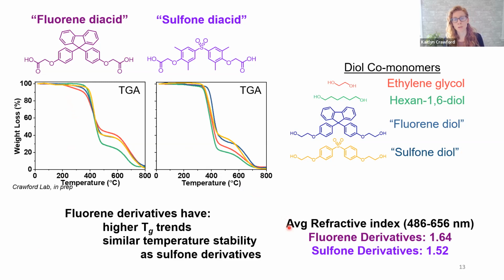Then another important component is that we maintain the optical transparency. This is really important for a number of applications, including in electronics. The fluorene derivatives are 1.64 on average for the refractive index, and the sulfone is a little bit lower. For a frame of reference there, the typical polymer is around 1.4 to 1.5 refractive index. And so a small jump to 1.6 might seem insignificant, but it actually can enable a number of applications that wouldn't otherwise be available for the lower refractive indices.